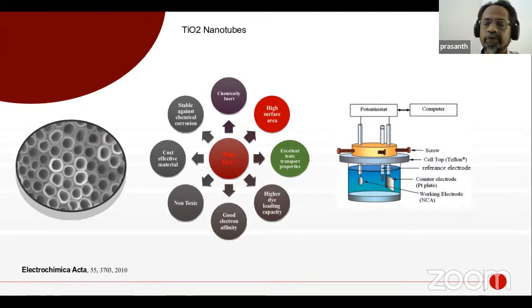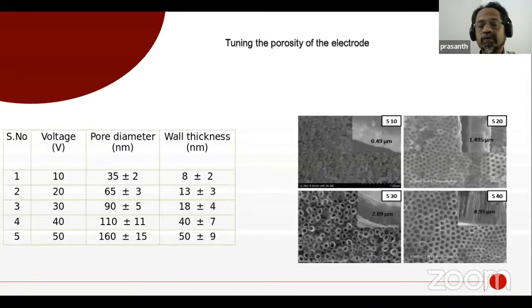And the nanotube fabrication is very simple. You can use an electrochemical technique to develop this material, where you use a titanium foil as an anode and a platinum electrode as a cathode, and apply some voltage. That's it. You have to play with the electrochemical conditions to tune the structure of your tube. That means you can play with your voltage. That's the first one you are applying.